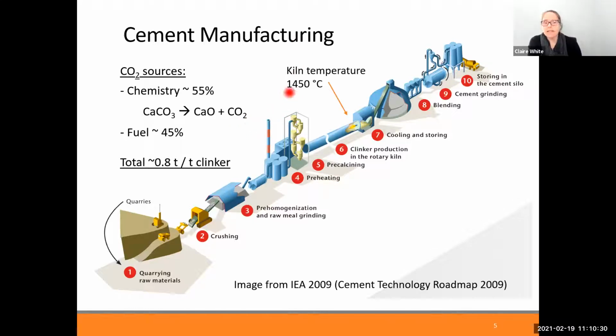And then also to get to these really high temperatures, in the past, people have used petroleum coke. It's a very good fuel for these cement kilns. And so obviously with combustion of petroleum coke, there's CO2 emissions from that as well. And so if you look at the divide of how much CO2 is produced by the decomposition of the limestone versus how much CO2 comes from the fuel source, it's about 50-50.